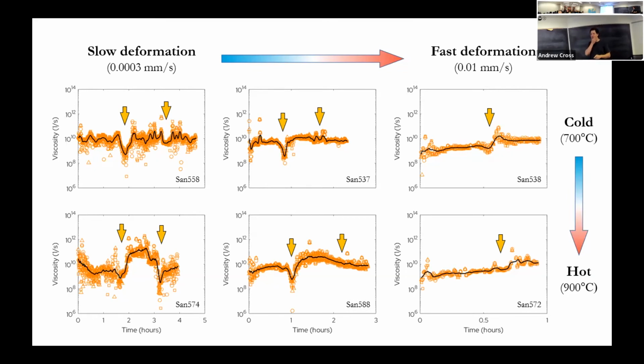Let's think about temperature first. If we compare the top row with the bottom row, the arrows here indicate where we're actually going through the phase transition. We'll see that, for example, for slow deformation under cold conditions, we get maybe an order of magnitude, maybe 2 orders of magnitude, of transient weakening and a decrease in viscosity right here. But then the viscosity recovers back to its initial value, maybe slightly higher because coesite is slightly stronger.